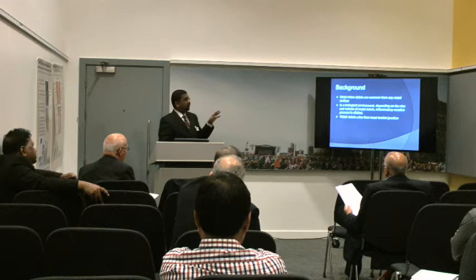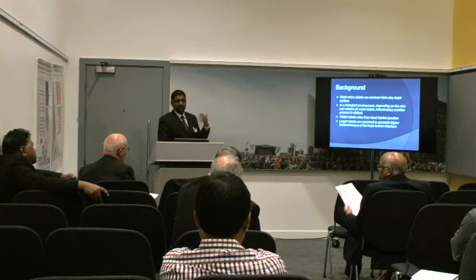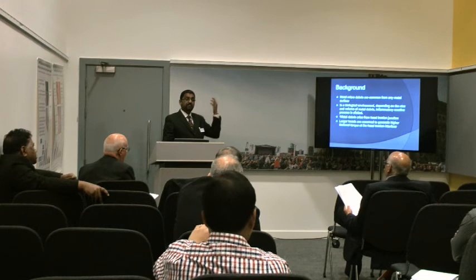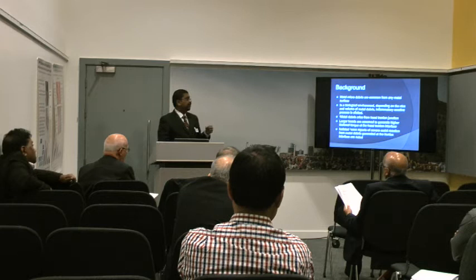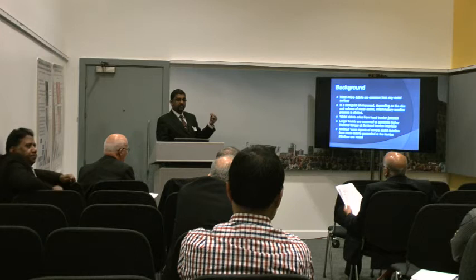Now, the metal debris can also arise from a head trunnion junction, and there have been isolated case reports here and there where we had to go in and revise it and found that the debris were not from the metal or poly. Even the case report which I'm going to show next is actually metal on poly, where the wear was from metal debris from the trunnion. So there is always a bit of concern about metal debris from these trunnion head interfaces.